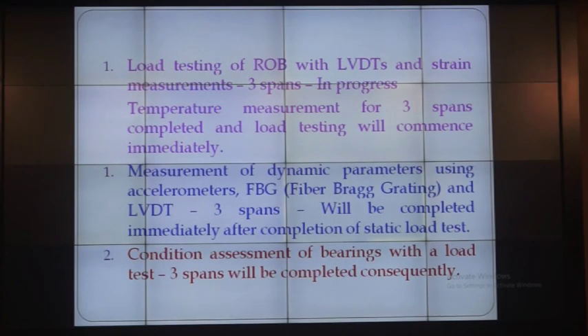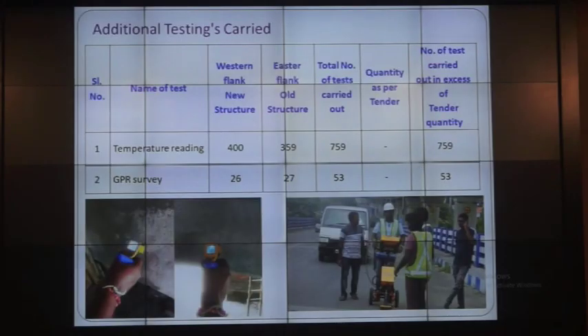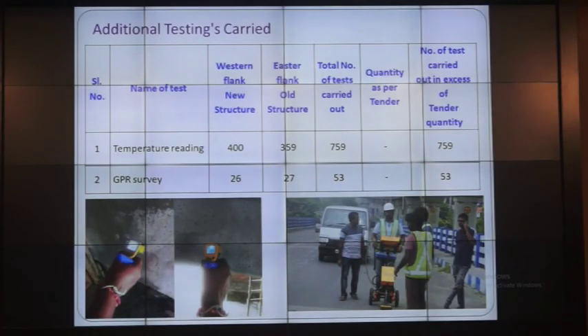Then we did the load test on the ROB with LVDTs and strain gauges, for the 3 spans. Temperature measurements for 3 spans completed. Yesterday we showed you whether there is some problem with the heat generation due to some collapse. Something is happening, so as a precautionary measure we took the measurement. And these were the things used there. You can see additional testing carried out, temperature. These are all beyond our contractual obligations.